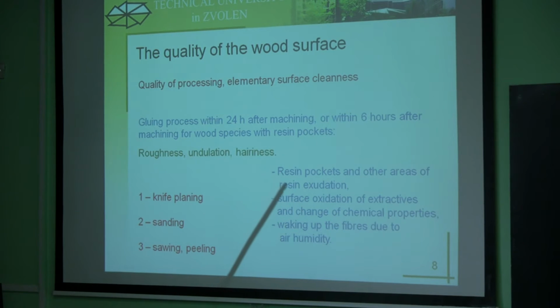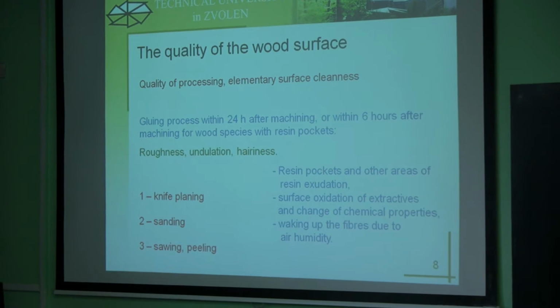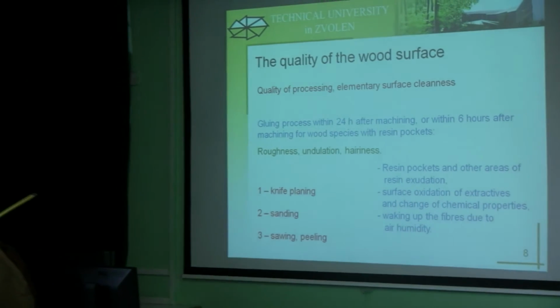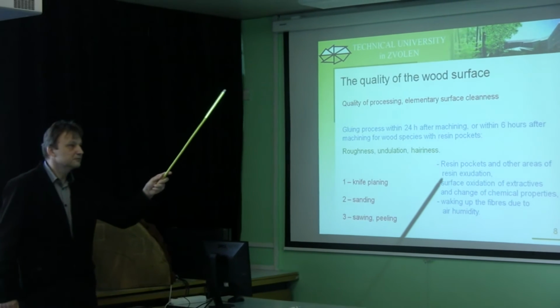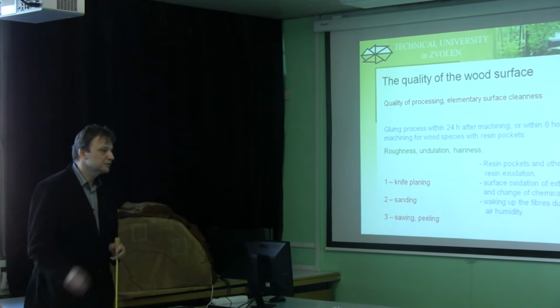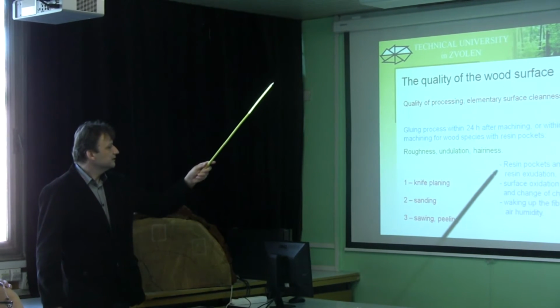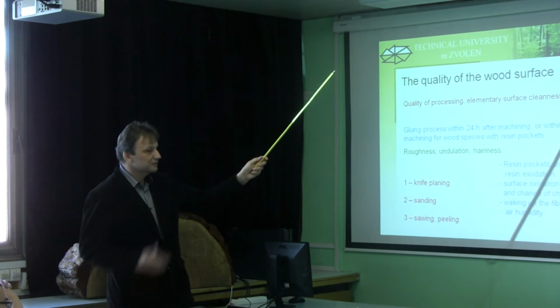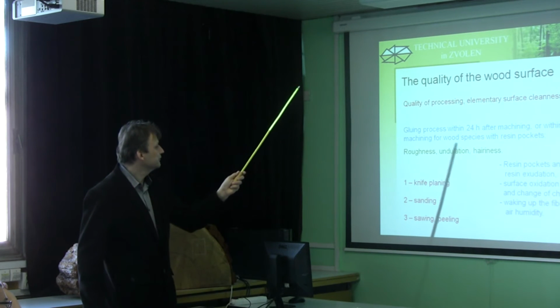If you have some wood species with resin pockets, there is the danger of resin flowing onto the surface, and in this case gluing is prohibited, or in this area is very problematic, because the resin has very high viscosity, and the pressure cannot spread this resin from this space. This is very often a problem when you are gluing, for example, larch or spruce, resin wood species. It is necessary to process the surface within 6 hours before gluing.